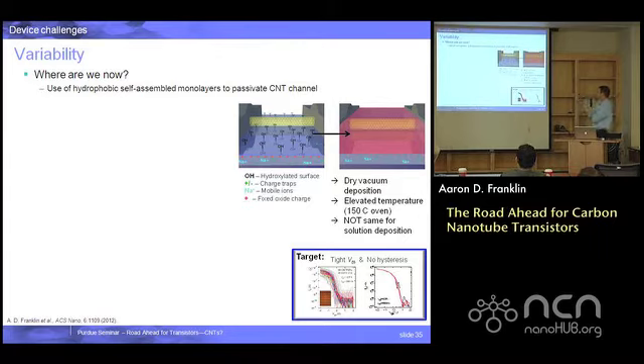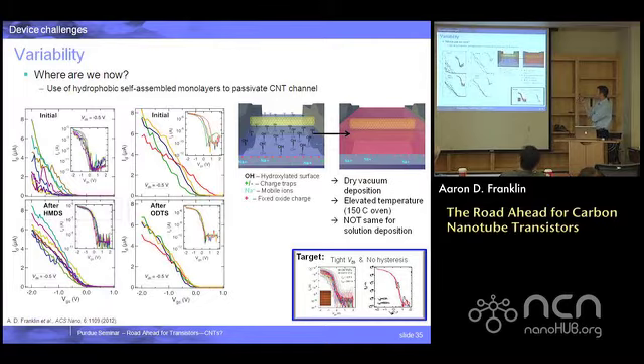So we did a pretty crude passivation layer, and I have another one I'll show that's better, but this is just an HMDS layer, deposited in a dry vacuum environment where you have some elevated temperature to help drive off the adsorbates, and then the HMDS serving as a protection from keeping the adsorbates from coming back when I put my sample back into the air.